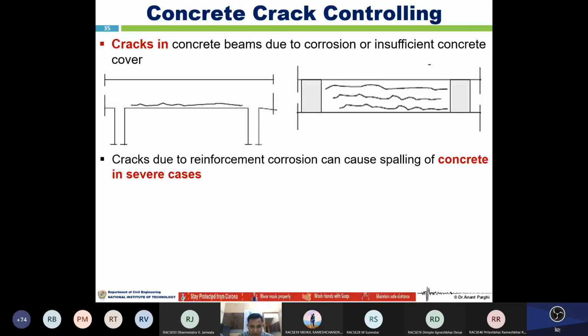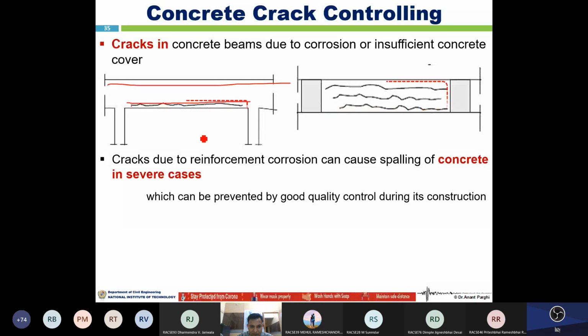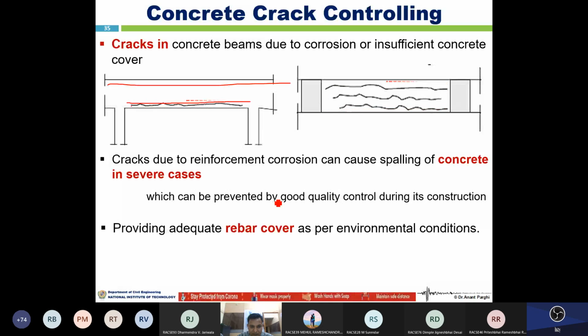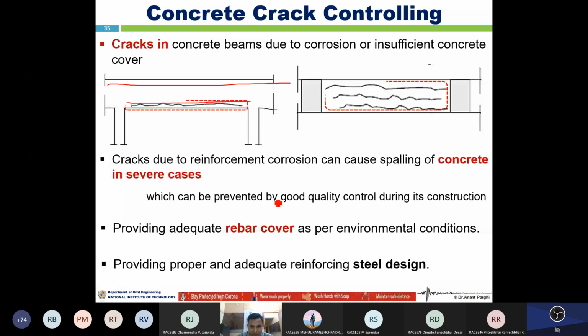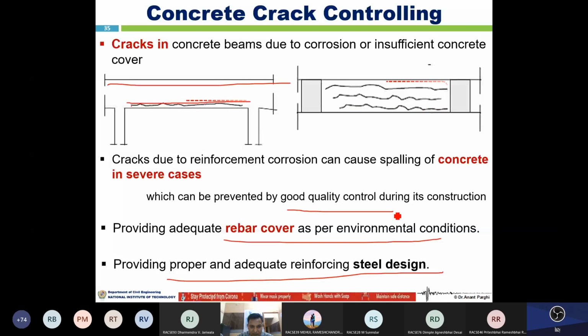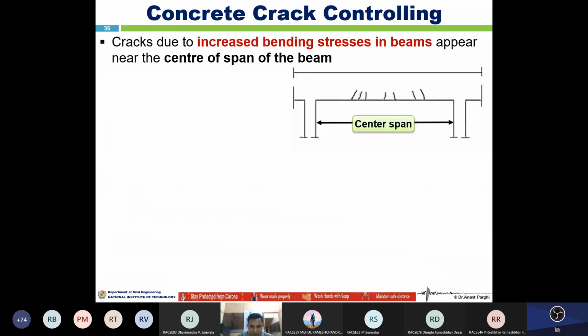Another crack in a concrete beam is due to tension, right? Because of corrosion, there is a crack going parallel to the reinforcement in this direction, like longitudinal reinforcement cracks developing because of corrosion. So how can we stop the corrosion? Reinforcement corrosion can cause spalling of the concrete in severe cases, which can be prevented by applying good quality concrete as well as proper reinforcement detailing and proper curing conditions. Like here, adequate reinforcement design, proper reinforcement cover, good quality concrete as well as proper curing condition. This way we can control the crack in construction practices also.